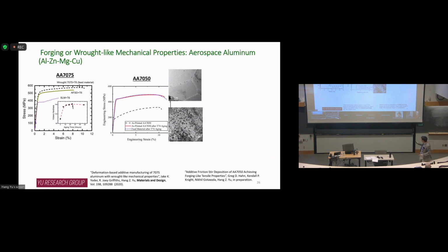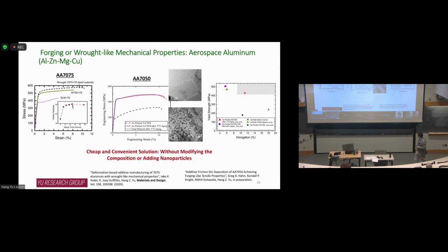But after heat treatment, you can get forging-like properties. Of course, we can make some kind of strength-ductility plot and show you that this process gives you properties probably falling in the regime of a forging standard. I think the take-home message is that when we talk about high-strength alloys like aluminum aerospace alloys, this process gives you a cheap and convenient solution to achieve good mechanical properties. And this is the advantage, especially in these high-strength aerospace-grade aluminum alloys.